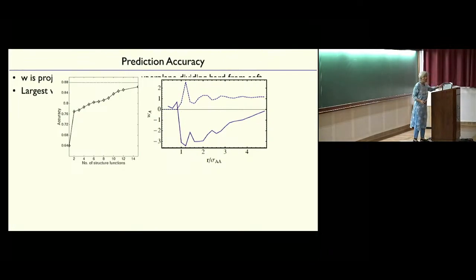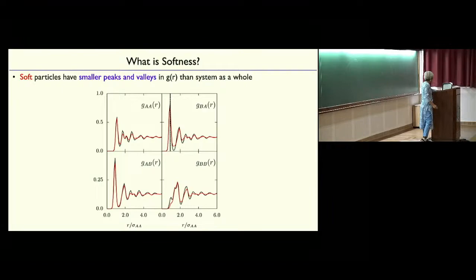Actually, with just a single structure function, GAA, the probability of finding an A particle at the height of the first peak for the average G of R, that already gives you 68% prediction accuracy. So it's not terrible. If I look at the average over the soft particles, the ones on the positive side of the hyperplane, in red, compared to all of the particles, in black, again the differences are at the peaks and valleys. I think of this as a quantification of the cage. There's a very old idea that a particle is trapped in a cage by its neighbors. How strong is that cage? The strength of that cage is determined by the height of the first peak, the depth of the first valley, the next peak, and so forth. And that's exactly what softness is quantifying. So it's measuring the strength of the cage.